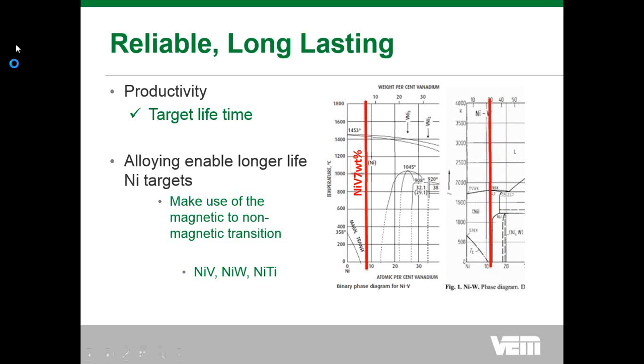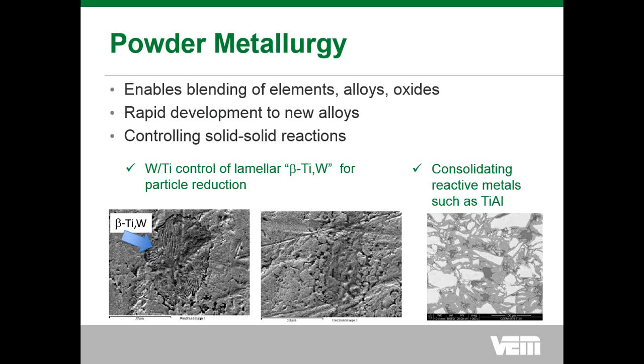And so again, depending on where I want to be in the sputtering process, I can tailor from a blend of almost all elements to a combination of elements and intermetallic. And again, if I go all the way, a long time at temperature, I may convert all of that to a single intermetallic phase. So again, powder metallurgy enables you to control the degrees of each type of phase being formed in your target material.